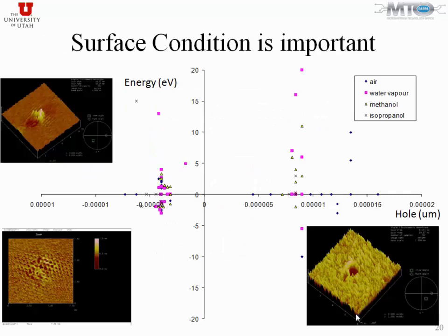So going back to the graphene problem, and we are repeating this with all our 2D materials, the question is how much energy, in terms of eV, it takes to pluck atoms from the surface of these 2D materials. Now, that's a simple question, but the answer is very complex. It depends on what you have on the surface. These are done in laboratory environments, so you can end up with water vapor in there. And if you happen to clean your sample with methanol or other types of alcohols, you may have residues in there, and those all affect the energies that you measure.